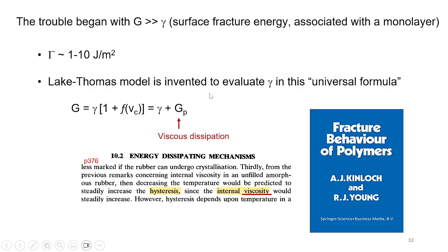So in my opinion, this is where the trouble begins. The G is no longer the surface tension; it is much larger. And if you look at it from this energy viewpoint, you have no way other than suggesting that the second term is all dissipating. And that seems to be consistent with the idea that the second term is changing monotonically with the rate of stretching, and therefore its origin is viscous dissipation. So that's the current paradigm, reviewed and discussed in our textbooks.